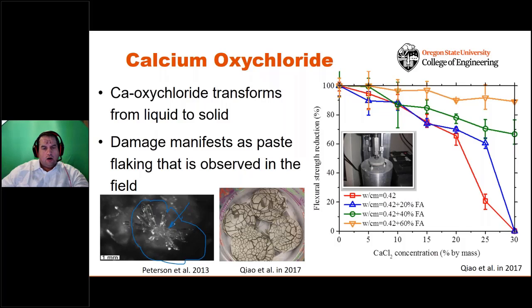One of the challenges is lots of times people will take a section, they'll polish that section and they'll look for the oxychloride and they won't see it. The reason they won't see it is because this is a very transient phase that has to do with relative humidity and temperature. I liken this a little bit to looking for Bigfoot, right? You might see a footprint and see that the oxychloride was there, but finding Bigfoot standing in that footprint is pretty tricky to do.